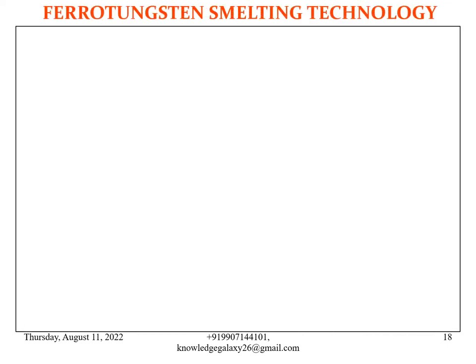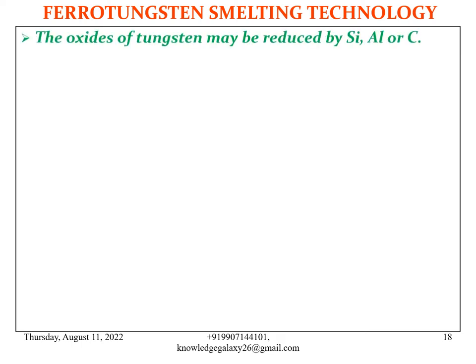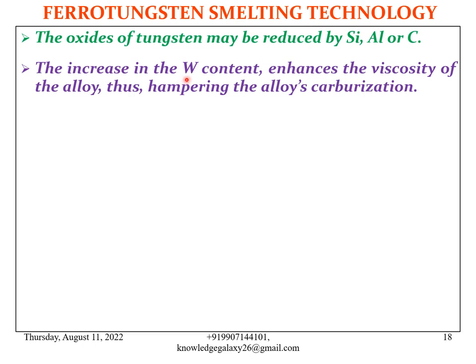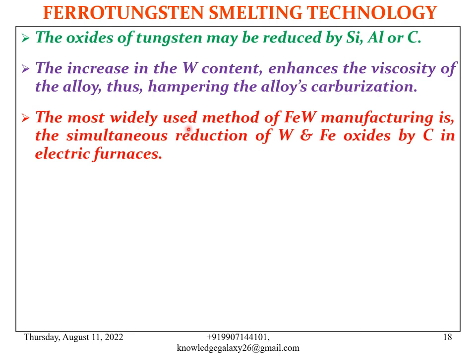My dear friends, let's proceed and discuss ferrotungsten smelting technology. The oxides of tungsten may be reduced by silicon, aluminium or carbon. The increase in the tungsten content enhances the viscosity of the alloy, thus hampering the alloy's carburization. The most widely used method of ferrotungsten manufacturing is the simultaneous reduction of tungsten and iron oxides by carbon in electric furnaces.